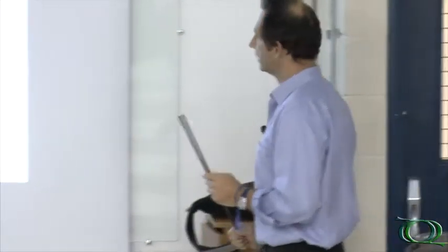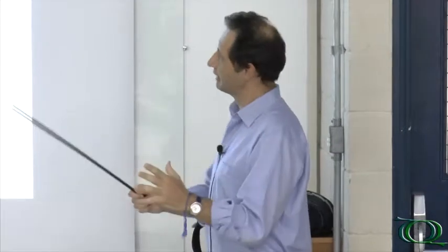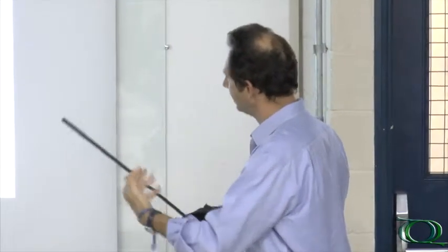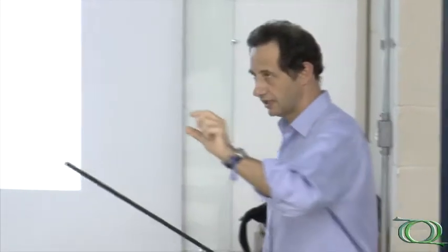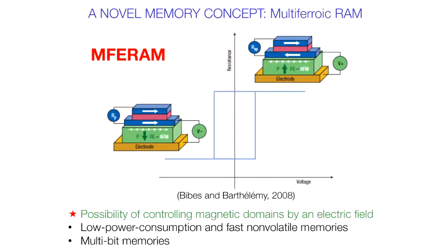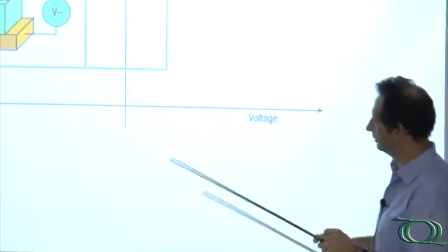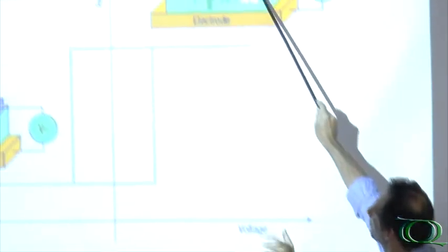So this suggests some new concept, because on one side, the ferroelectric memories are faster, but on the other hand, the signal is low, the voltage measured. And the coupling between ferroelectricity and magnetism offers an opportunity for having a big signal without injecting current. So the idea is that you polarize a multiferroic material, which is at the same time ferroelectric and magnetic, in this case antiferromagnetic. So you polarize with negative voltage and polarization is downwards, or positively, and you have a polarization upwards. And because of the magneto-ferroelectric coupling, the magnetization changes. So if you put a sandwich of magnetic material, the magnetic material on top will also switch the polarity.